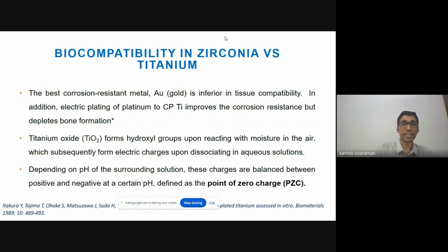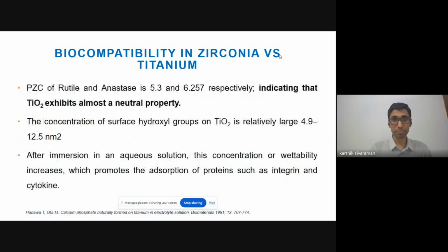So moving on to the titanium oxide, we know that there is a layer of titanium oxide formed over the surface of titanium. It reacts with the moisture present in the air to form hydroxyl groups, which subsequently form electric charges upon dissociating in aqueous solution, like body fluids. Depending on the pH of the surrounding solution, these charges are balanced between positive and negative at a certain pH, defined as the point of zero charge. So basically, the point of zero charge is a gauge of the acidic or basic property of a surface oxide and will vary with the material.